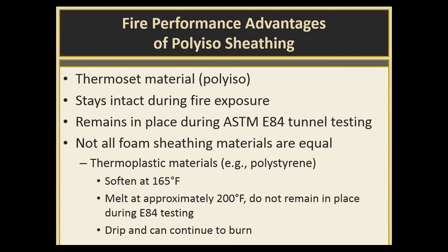And the best analogy I can give is think of a stick of butter versus a piece of bread. If you take a stick of butter and you place it near a heat source, if the heat gets warm enough, it will start to change form or shape. If you move the heat source, it will cool, but it'll be in a different shape than when it started. And if you expose it to direct fire, it's going to melt and drip and eventually puddle. And that's how thermoplastics perform in fire environments. So they don't do well in fire tests specifically.